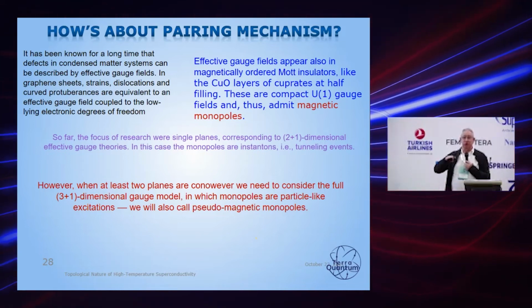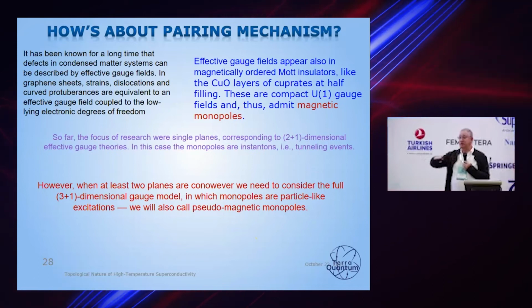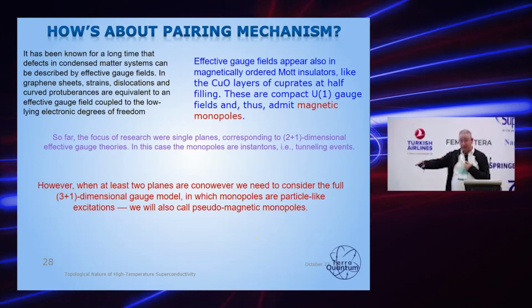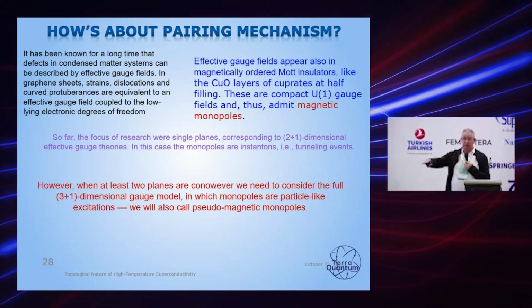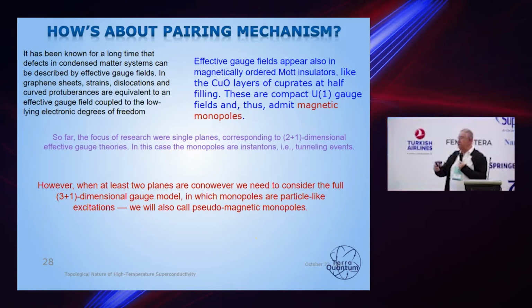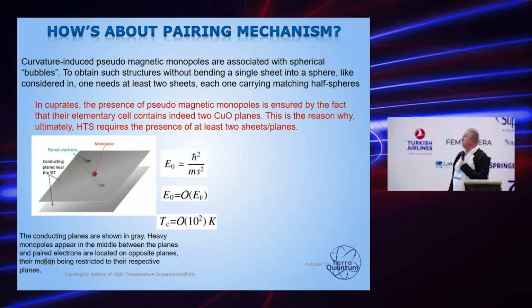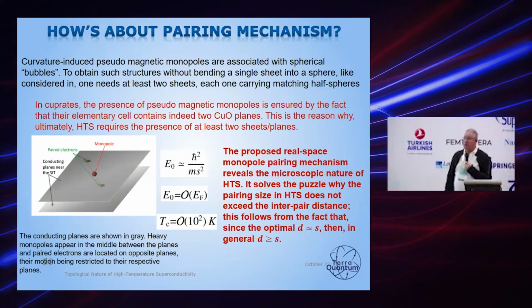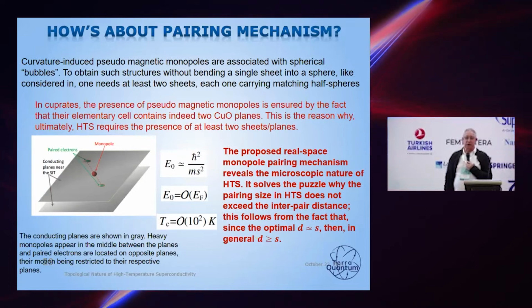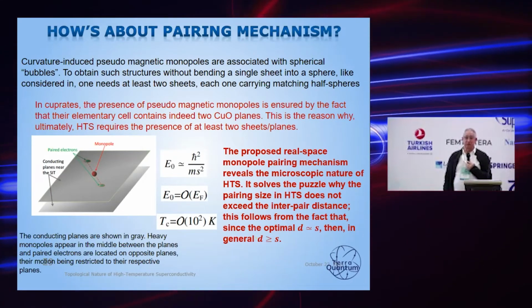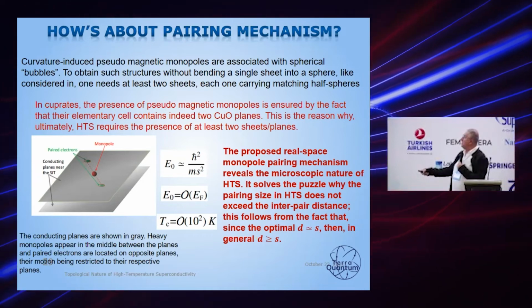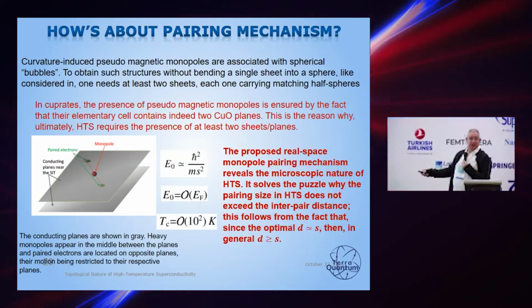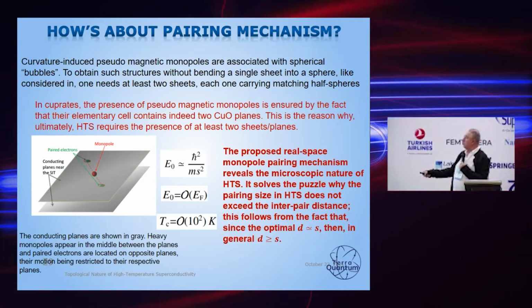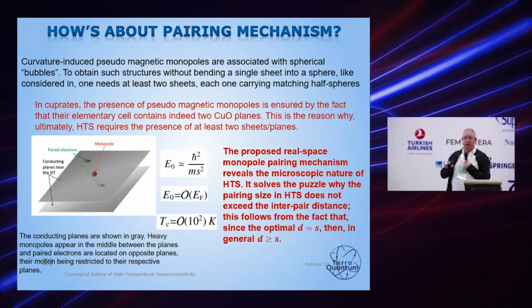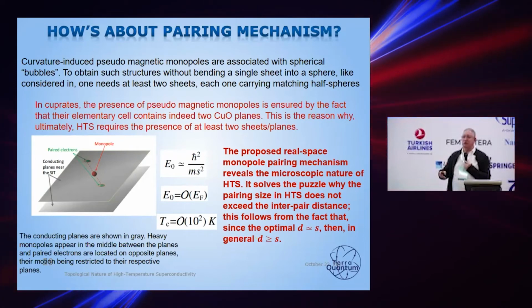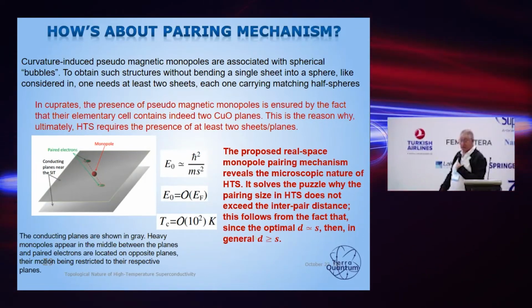So we can say that if we do have these topological defects, for example, in the cuprum oxide plane, then we immediately have a local pseudomagnetic field, and it means that we do have these pseudomonopoles there. And then we can consider a very simple model. Actually, it's again a simple problem from a standard quantum mechanical course. So consider two conducting planes which have this pseudomagnetic field, and then it means that in between these planes we have this pseudomonopole, which exactly produces this pseudomagnetic field, which describes this curvature caused by the topological defects there.